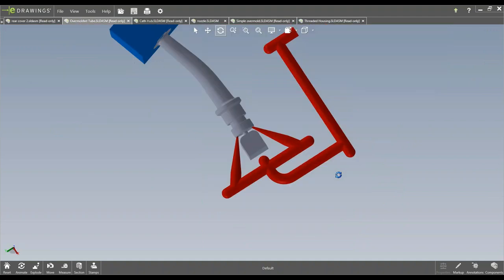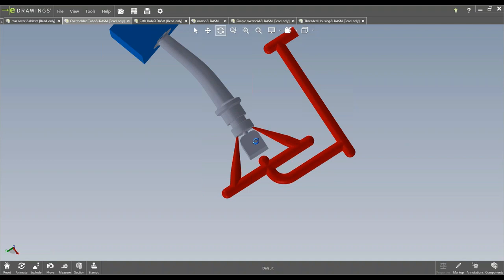So kind of go back to this one. I'm trying to get the flow of the plastic down through the part rather than come in from the side perpendicular. And then you've also got the hand load in the area there as well. And if by 90 you mean coming in from the side of a diameter, just as far as flow and fill goes, it's just a better location. The tube over the tube there is very flexible, so we're trying to keep that as straight as possible for as long as possible, starting at the start of the tube and then going along, trying to keep it central.